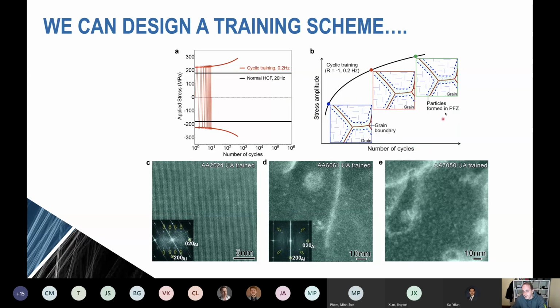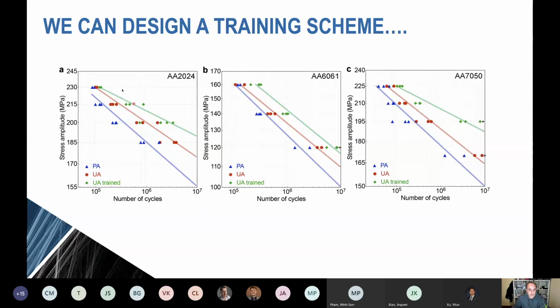And what it does is it generates dynamic precipitation. We design this very carefully to specifically get dynamic precipitation in the precipitate-free zones to try to minimize the strength contrast between the grain interior and the grain boundary regions, and then do a normal high cycle fatigue test. And that's what's shown on the green curves here, and you have even further improvement in the high cycle fatigue performance. And so if we look at something like a 7000 series alloy, which is used in the aerospace applications, we're talking about something like an improvement in the high cycle fatigue performance, let's say lifetime, of maybe a factor of 30 or 40 compared to the traditional peak age state.